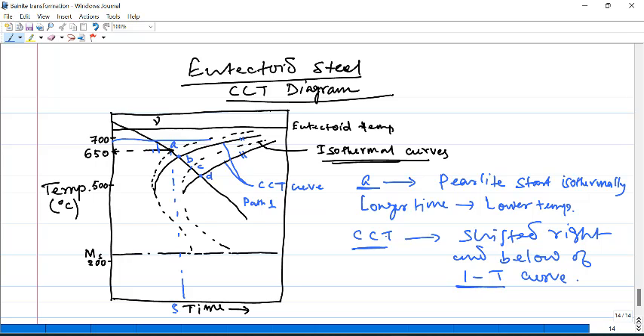When talking about practical heat treatment of steels, it is most of the time continuous cooling — including martensitic transformation, which is simply quenching. Even without quenching, heat treatment is generally done by continuous cooling rather than isothermally holding at a constant temperature. Notice there is no bainite curve in the CCT diagram — and that is not an oversight. In continuous cooling, bainite does not form. This is simply the case.